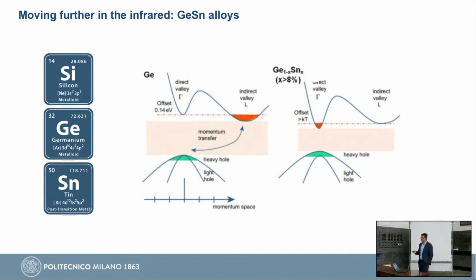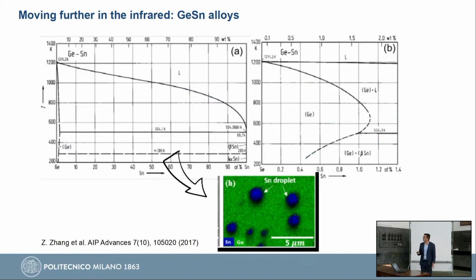Now the issue is that germanium tin is not as forgiving as silicon germanium. So if we look again at the phase diagram, here you have the full phase diagram between pure germanium and pure tin. This is just a zoom of the first 1%. Essentially, we can obtain an alloy of germanium and tin only for a few, like 0.5% tin content, which is not useful for anything.